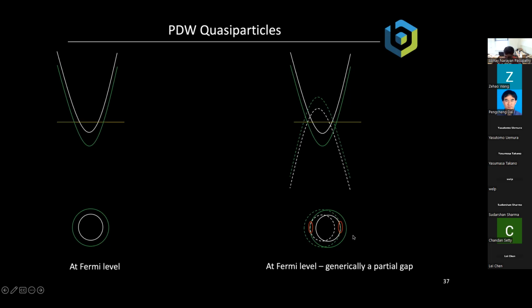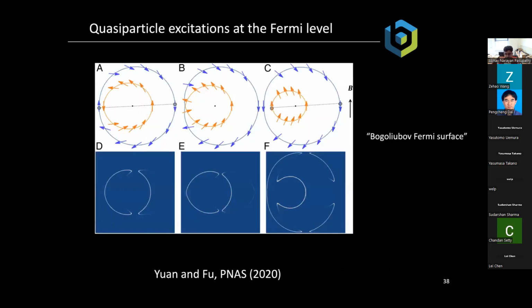And so this is one of the predictions of these types of superconductors, these spin density wave superconductors or FFLO superconductors, that generically at the Fermi level, the superconducting gap will not be on the entire Fermi surface. It could be, depending on the strength of the superconductor. But generically, there will be regions of the Fermi surface where there are quasiparticles even at the Fermi level. And this is something quite unique. A regular superconductor has no quasiparticle excitations at the Fermi level. You have to go to an energy delta above the Fermi level in order to see these excitations.